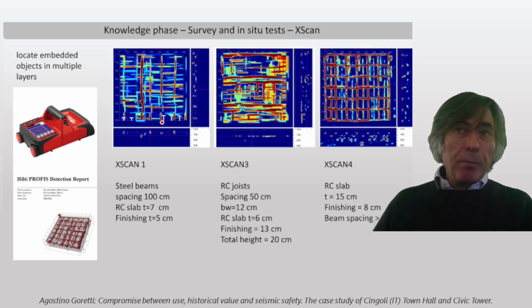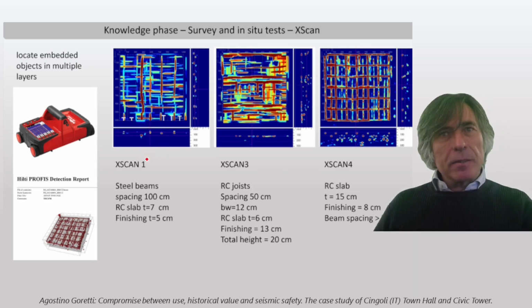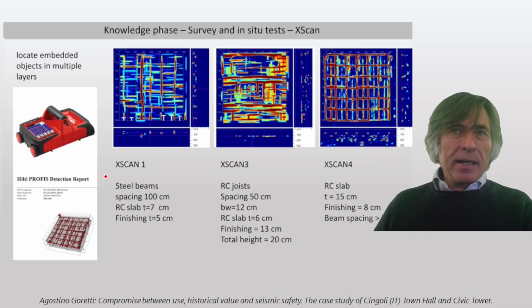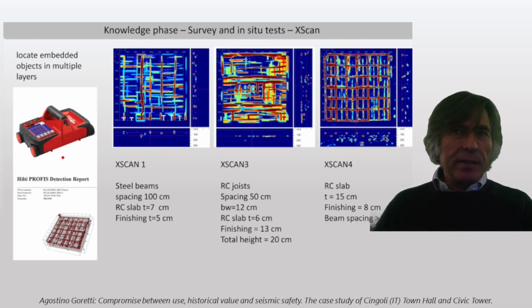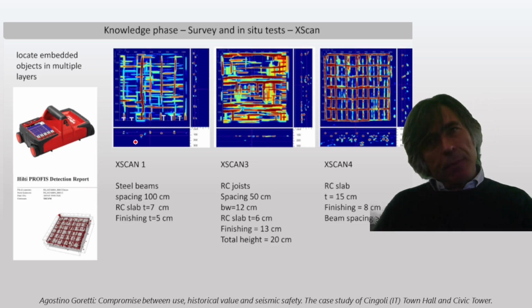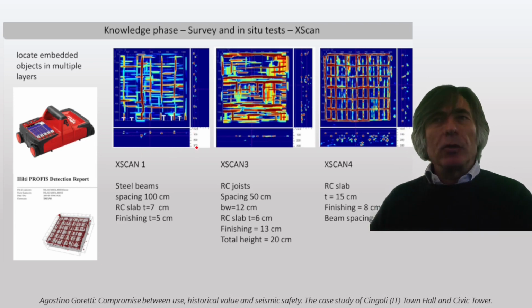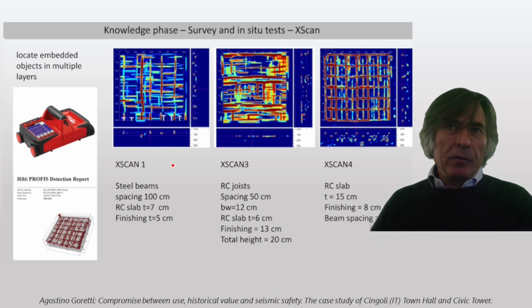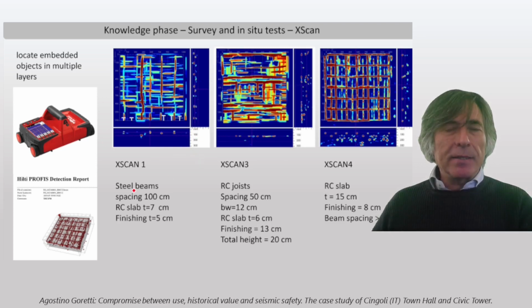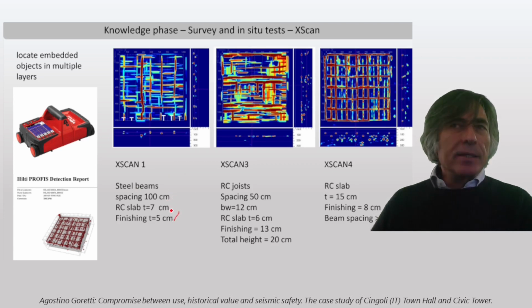Information on the floors, or confirmation of what we had from the design, has been obtained through the X-scan test. The X-scan instrument is a georadar with 3 antennae, which is able, due to these 3 antennae, to evaluate the properties along the thickness of the elements. So you have information on the reinforcement in the 2 directions in plan and on the thickness. This gives you 3D information from which you can get, for example, the thickness of the finishing, the thickness of the slab, or the spacing of the beams, and sometimes also the thickness of the joists, and so on.